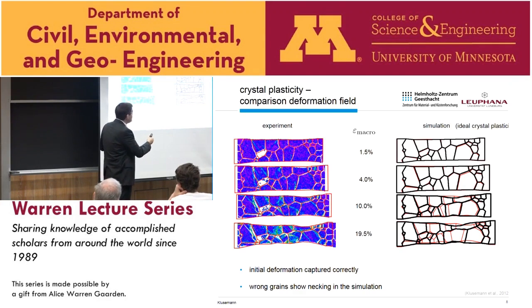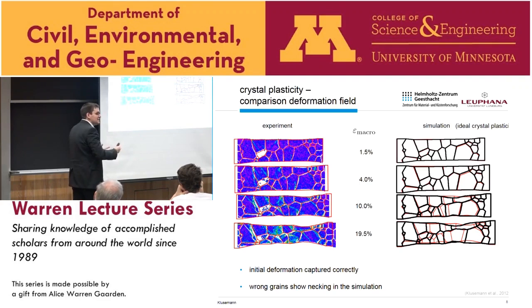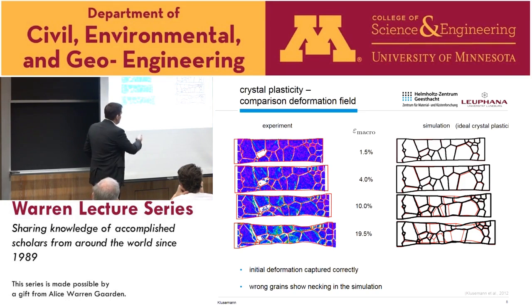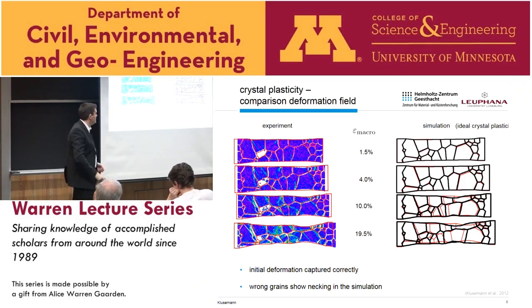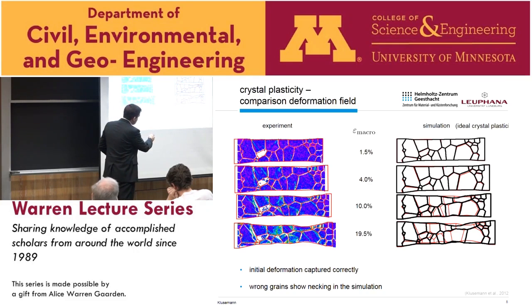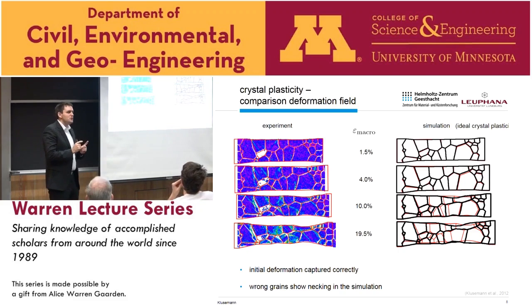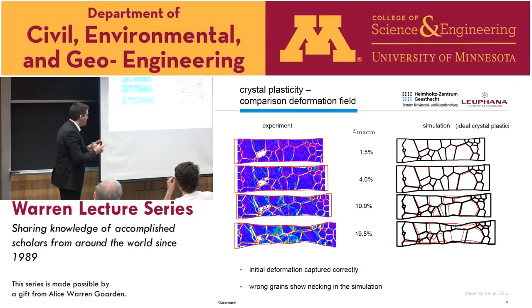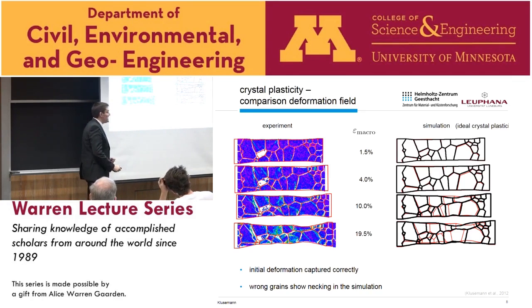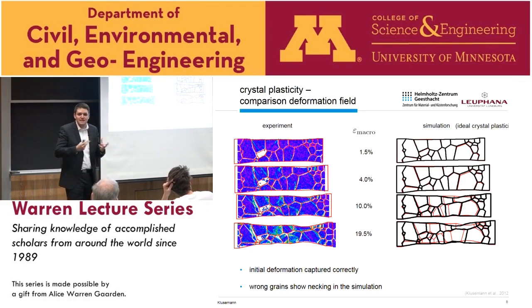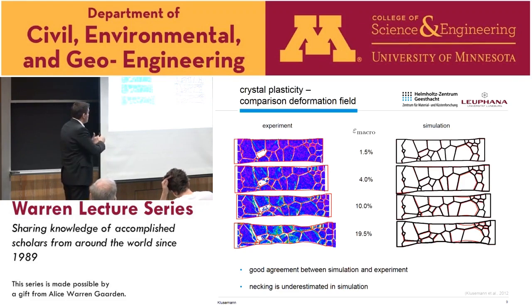And what you can see is that in the beginning, you cannot really see a difference. It looks like we initially captured the deformation correctly. However, as soon as the deformation gets large, and we assumed here an ideal crystal plasticity model, so no hardening, we see a large deviation, and in particular we see that we get in the simulation a kind of necking behavior in these grains, which represent this one and this one. This was not the region which showed the largest deformation in the experiment. So there's a wrong, I name it simply necking, prediction in this model, but this was not surprising, as we assumed an ideal plasticity model.